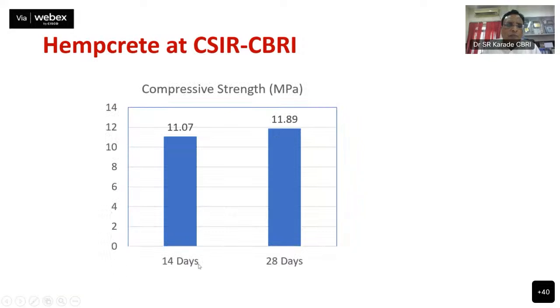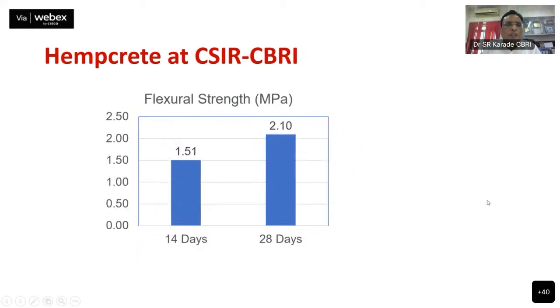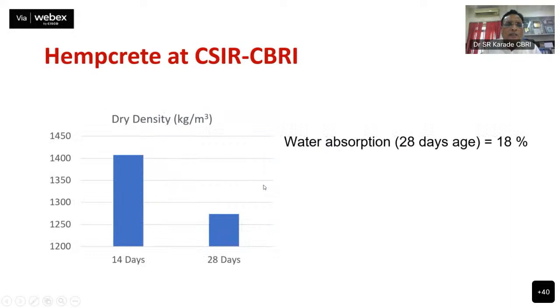Now you can see in 14 days itself, we can get most of the strength here. In 28 days, we can get around 12 MPa. Then flexural strength in 28 days, we get more flexural strength. Water absorption is around 18 to 20%, while dry density reduces with time because of drying of the hemp particles.